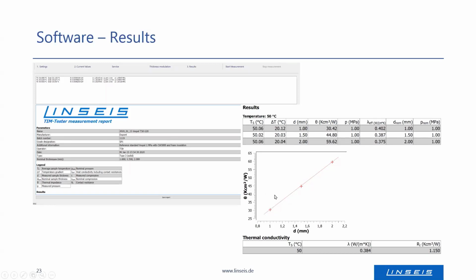In this example, a solid was measured where 3 different thicknesses were defined, each with a contact pressure of 1 megapascal. One can see the sample temperature, the temperature gradient over the sample, the measured sample thickness, the measured thermal impedance, the measured pressure, and the effective thermal conductivity, which is calculated for each single measurement using the sample thickness and the thermal impedance.